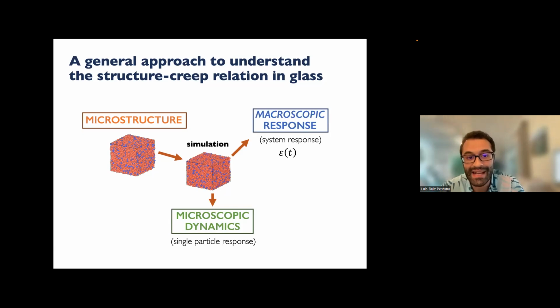So this I have in italics because if you are doing MD, typically the system sizes are small. You use periodic boundary conditions and you take care of the fluctuations because of thermodynamic fluctuations due to the size of the system. You can have access to the macroscopic response of that system, so the bulk response. But in any case, when I say macroscopic response, it's not associated per se to size, but it's the system response. So for example, you compress this box of glass and you have a strain over time, and that would be a system response.